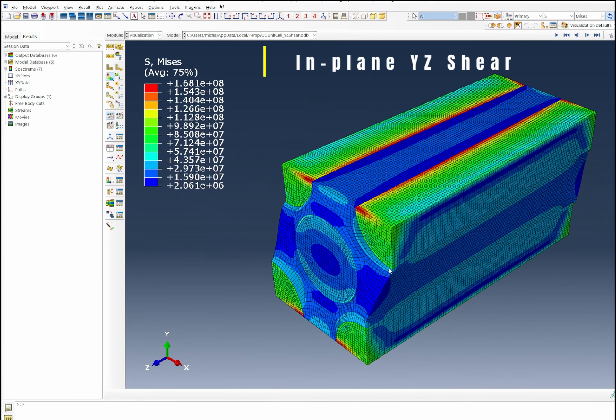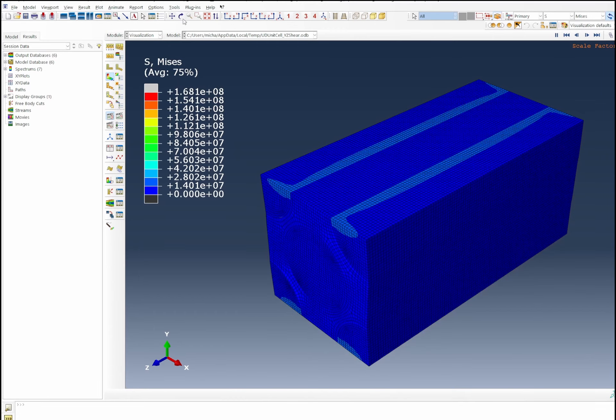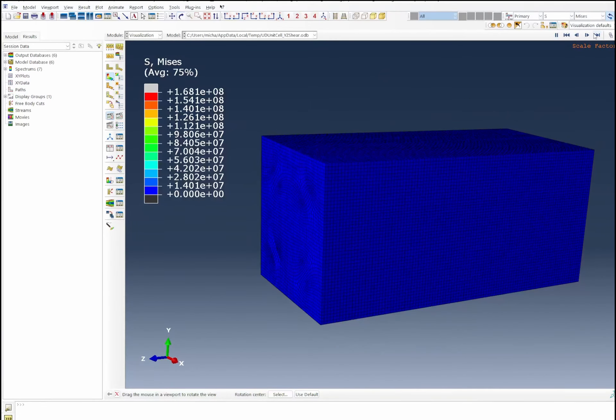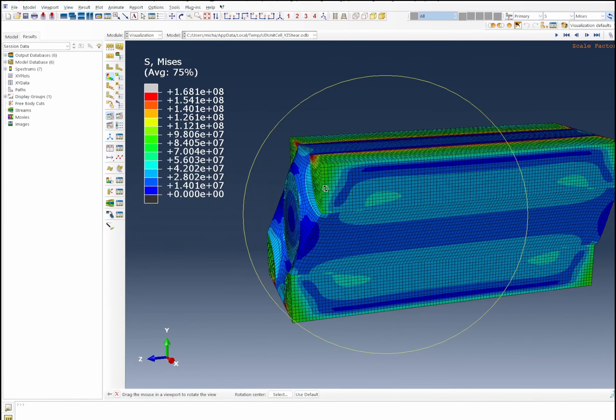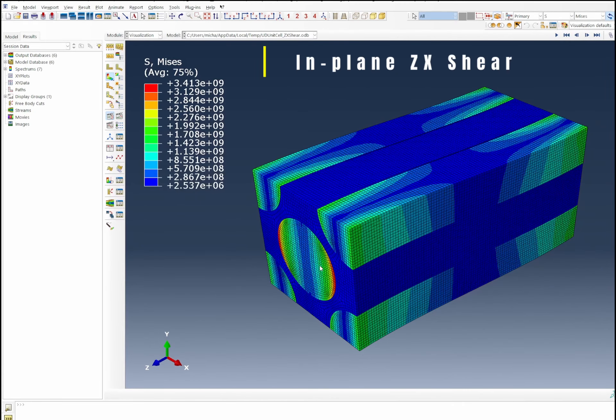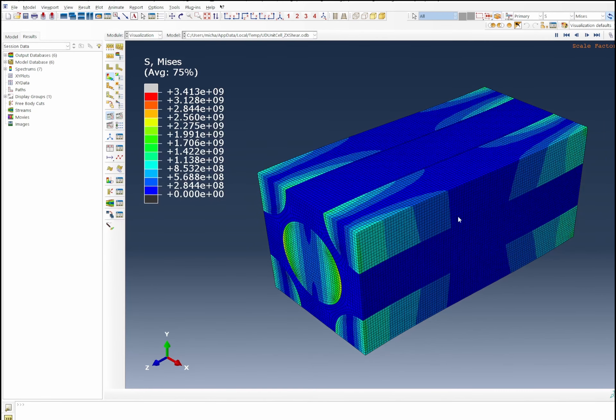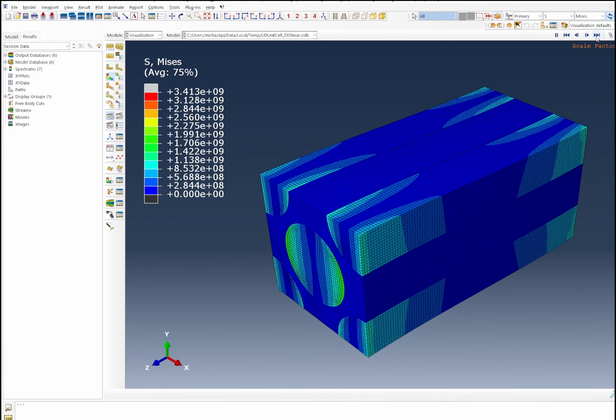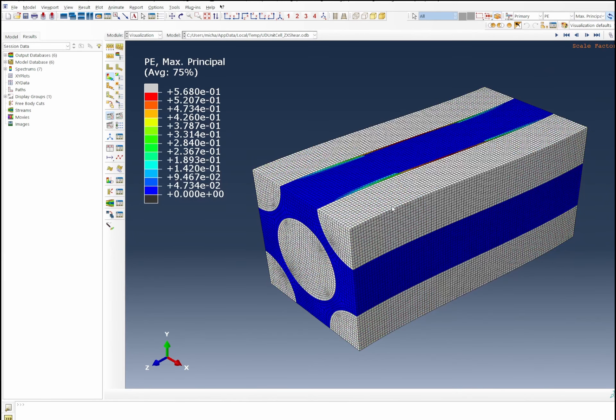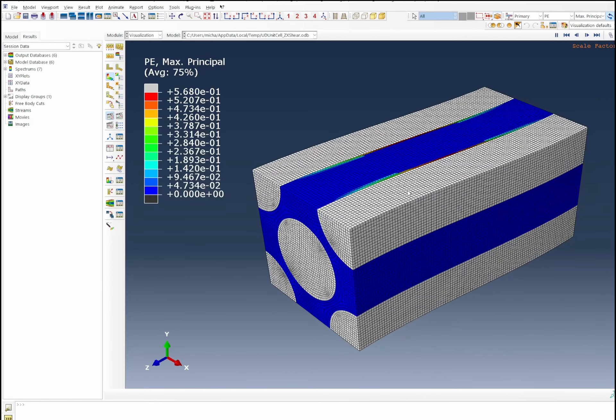The YZ shear shows the body being sheared on top with interesting behavior along the edge, showing the shear deformation in the YZ plane. The fiber at the front deforms significantly. The ZX shear is the last case, showing deformation in that direction with the fiber undergoing a buckling or kinking deformation. Looking at the plastic strain, most loading is concentrated along the edges of the fiber.